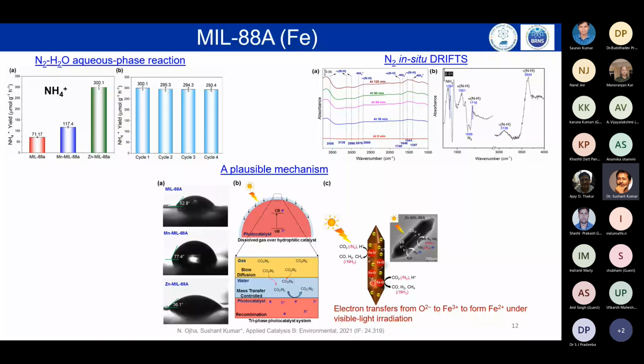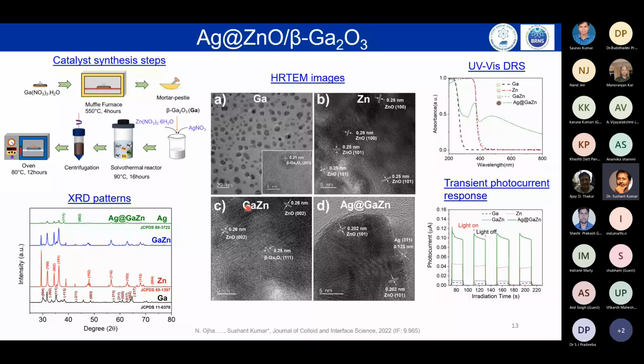Now, the final work, which I'm going to show you now, is silver decorated over zinc oxide and the beta polymorph of gallium oxide. Gallium oxide has a very wide band gap, which requires a lot of energy. Now, why are we interested in it? As I told you earlier, we have to have a favorable conduction band position and valence band position, so once we have a very wide band gap, that means we have a large thermodynamic driving force for the reaction to happen. That is being provided by the gallium oxide. Now to bring it down, one can use the zinc oxide and then use the plasmonic effect of the silver. And hence this was the basic concept behind designing this photocatalyst.